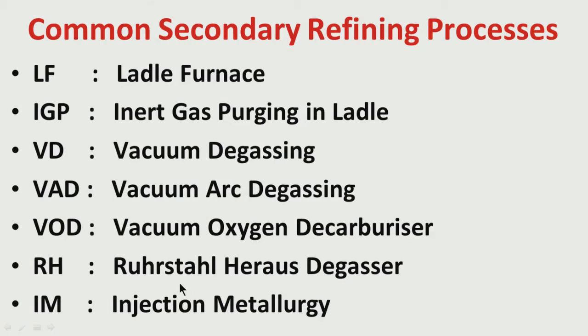It was invented in Germany, so it is known as the Ruhrstahl-Heraeus degasser, RH degasser. Then there is a possibility of injection metallurgy. That means you are injecting either some powder or some wire of calcium. So, injection metallurgy is possible in the ladle. By that process, you can get better control of the inclusions. I will come to that later on.